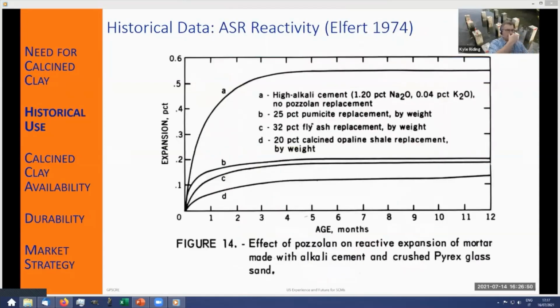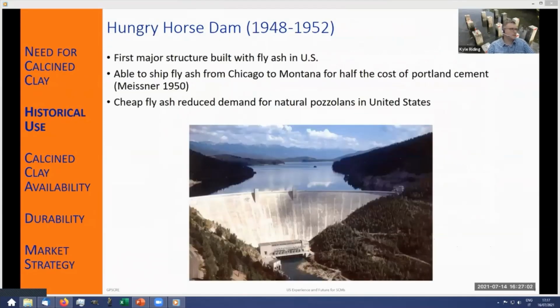Its ASR reactivity was really good, and better actually than fly ash in many cases. So really good performance from this material, and that's why it was originally used, because of performance, not because of sustainability. Our use of fly ash really started to increase when the Hungry Horse Dam was made in Montana. It was available almost for free because it was just being landfilled from the coal combustion. And so people started to use fly ash not because of performance, although it did perform pretty well. They started using it because it was available in cheap quantities, in massive amounts.